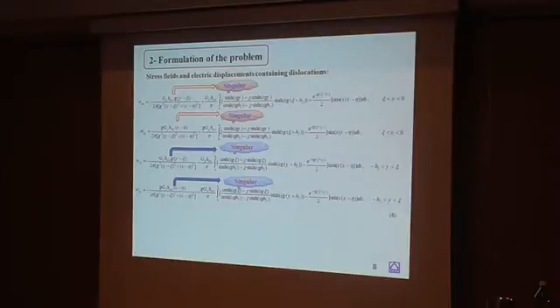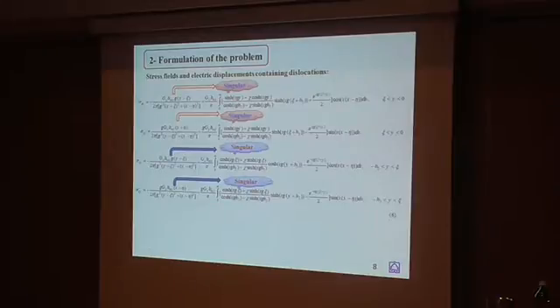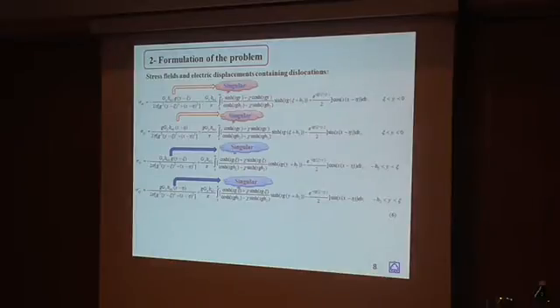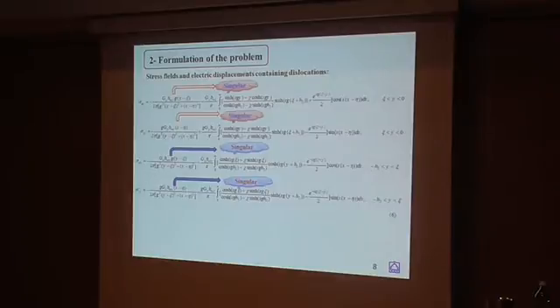After some mathematical manipulation reported in the paper, the stress field and electric displacement containing the dislocation are presented in equation 6. As shown, we can identify the singular term: the first term of the stress components is the singular term, and the integral in the second term is regular, so there is no problem in computation.